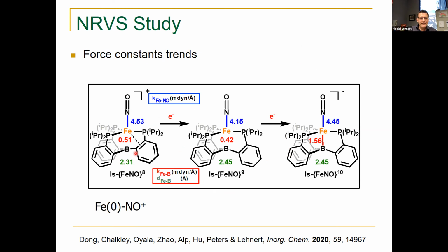So here is the 8 compound with the iron 0 NO plus type electronic structure, and the iron NO force constant is about 4.5 millidyne per angstrom. If you add an electron, you can see the bond becomes a little weaker, but that's mostly due to spin polarization effects, because in the 9, now you have 1 unpaired electron as an S=1/2 compound. If you add another electron, you end up with the 10, and in the 10, you can see that the iron NO bond recovers almost the same force constant. And what happens here is that you can see the interaction with the iron and the boron really becomes stronger in this doubly reduced compound, and that buffers some of the extra electron density that is sitting on the iron, is actually in a way stored in this inverse state of a bond here.